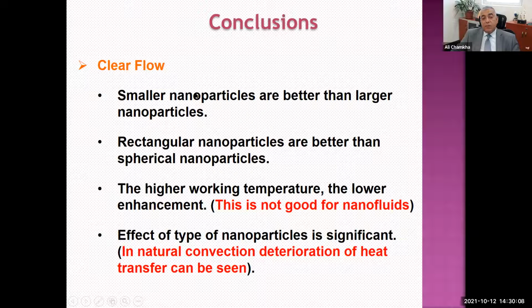For clear fluid, we found smaller nanoparticles are better than larger nanoparticles. Now, it differs for porous media. For porous media, rectangular nanoparticles are better than spherical nanoparticles. Again, for clear fluid, the higher the working temperature, the lower the enhancement. If you increase the working temperature, you get lower enhancement. This is not good for nanofluids. Effect of type of nanoparticles is significant. In natural convection, deterioration of heat transfer can be seen.